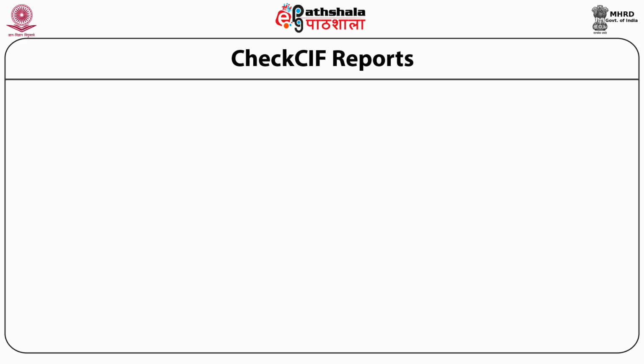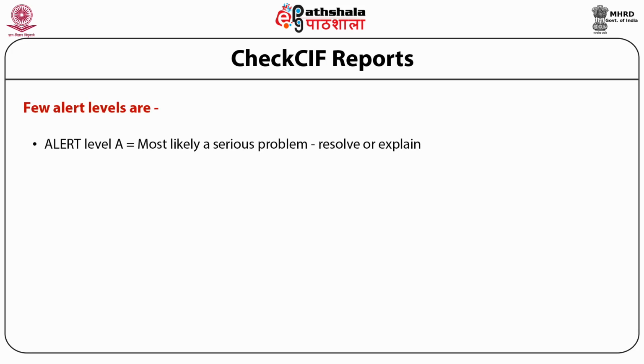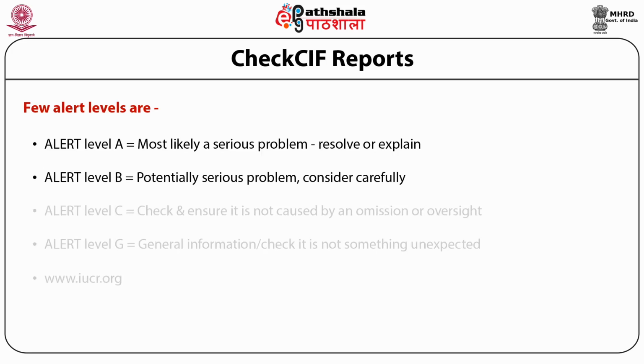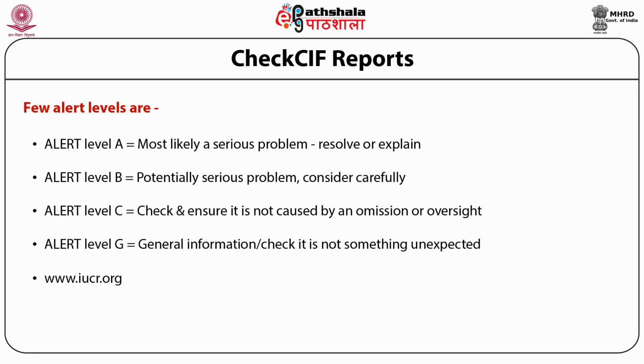Before depositing in the Cambridge Structural Database, the International Union of Crystallography has certain checkpoints where you submit the CIF file to check whether any error is present in the data or in the model. There are several alerts that will show up. Alert A indicates there is a serious problem; one has to really go deep and check the data refinement. Alert B indicates a potentially serious problem. For Alert C, we have to check and explain where the error could have been caused.